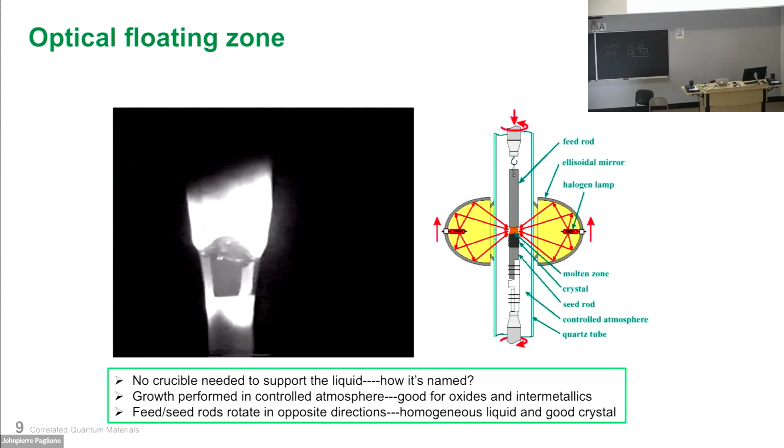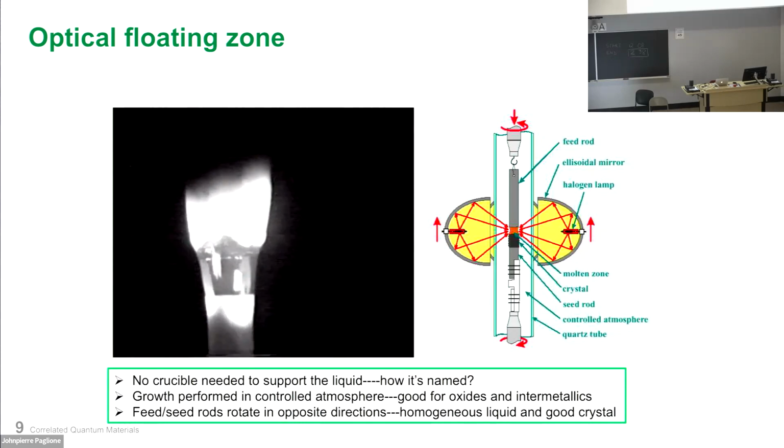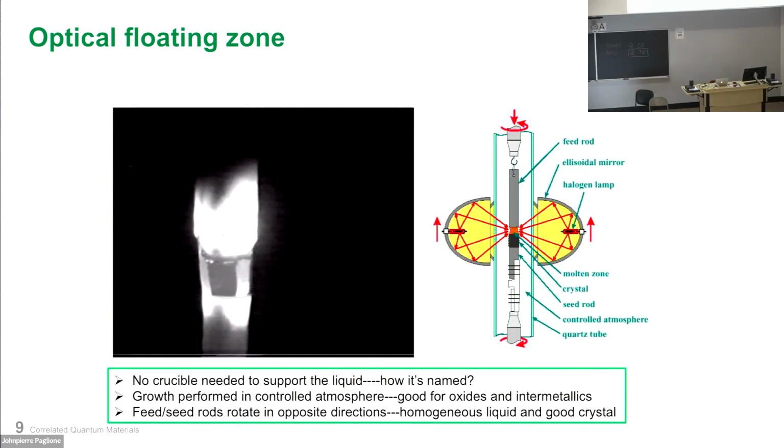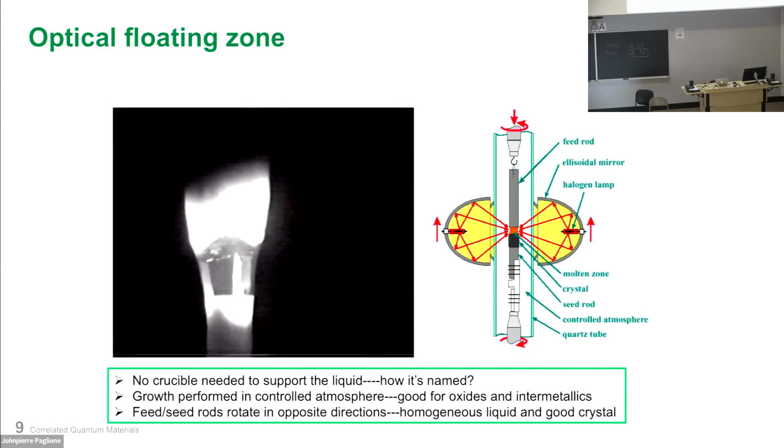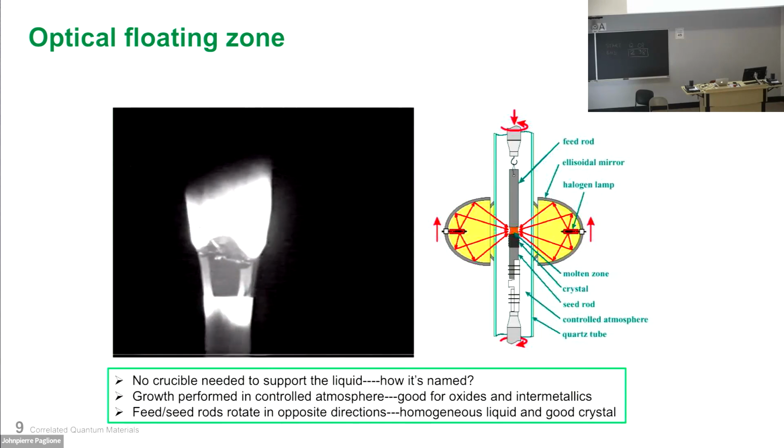How big do they have to be for this? Like, how big do you need to make the rod? As long as you can make it, that will give you a much better chance. The diameter is important too. It's harder to grow single crystals if it's too thick. So typically they're like 6 millimeters, quarter of an inch in diameter, and maybe 20 centimeters long.